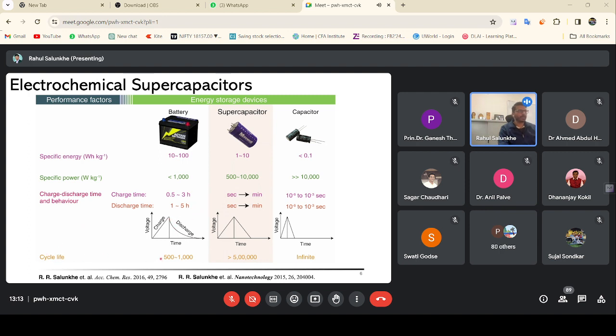Now, the cycle life is the last factor. The cycle life of batteries is about 500 to 1000 cycles. That means that after a certain cycling performance, the battery performance gets degraded because of material degradation or other chemical changes occurring in the battery, so performance degrades with time. Whereas in case of a supercapacitor, we can go over 5 lakh cycles of charge discharge. That means their lifetime is much higher compared to that of battery systems. And in case of a capacitor that we use in our normal electronics, we know that they have an infinite charge discharge life. So we can charge and discharge these devices a huge number of times. This is the basic difference between these three kinds of devices.